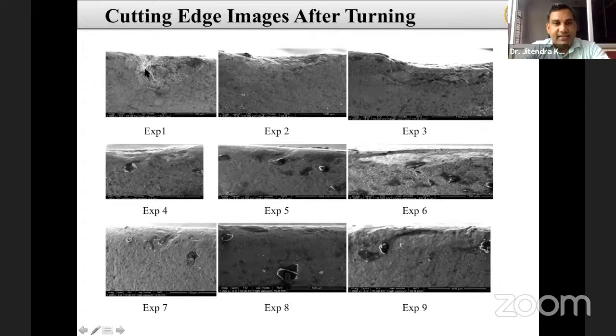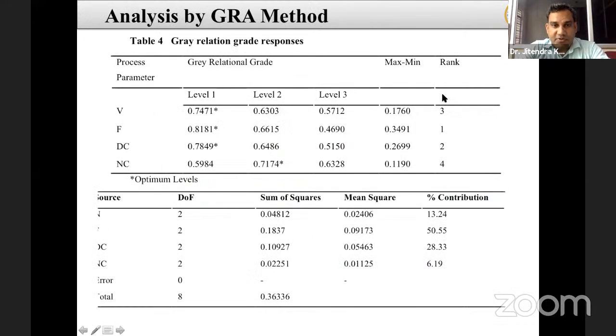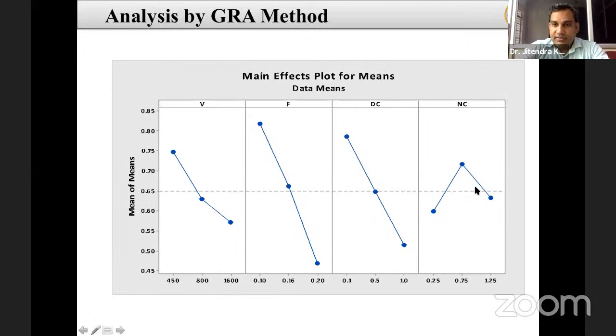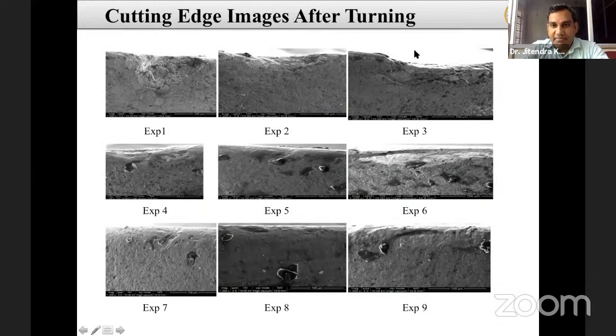Here you can see the flank wear on the cutting edge of the tool, and you can see the more flank wear. That's why the forces in experiment 3, you can see, are the highest, 414.658 Newton, and the surface roughness is also more or less higher. You can see this in these same images. It confirms that experiment 7 gives our lowest forces and also a better surface finish. No wear mark was obtained in experiment 7, but in other cases we obtained somewhat minimum or, in some cases, the maximum flank wear on all the cutting edges.